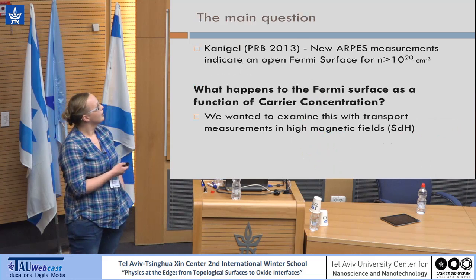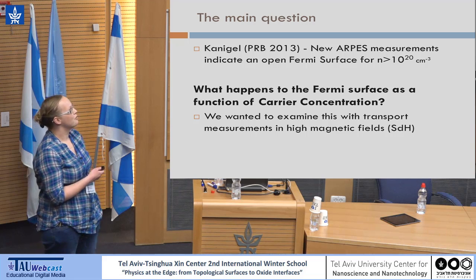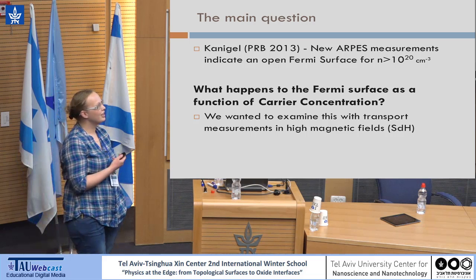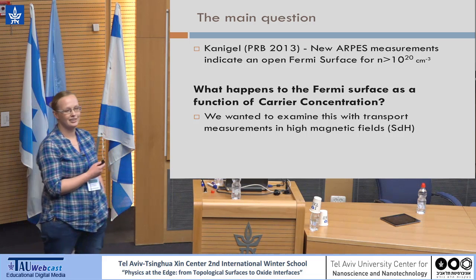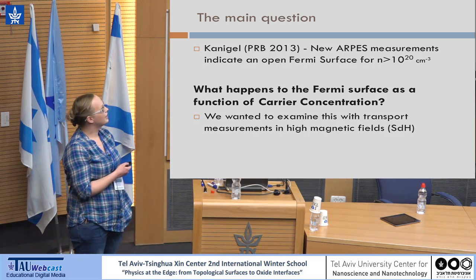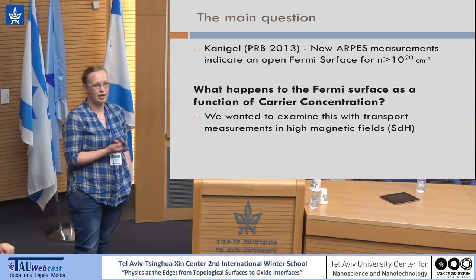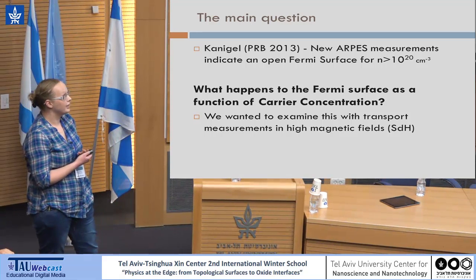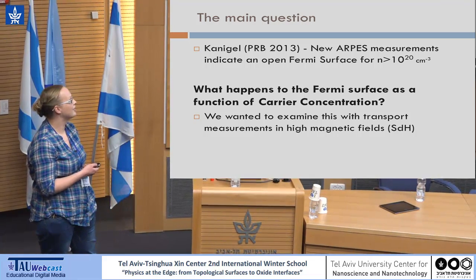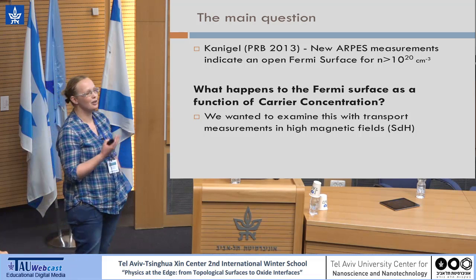Later, Amit Kanigel's group performed ARPES measurements using their special bulk-sensitive technique — which Amit Rybak will present in the next talk — and they showed that the Fermi surface of the bulk of copper-doped bismuth selenide is actually open. So what we set out to examine is whether the Fermi surface is open or closed.